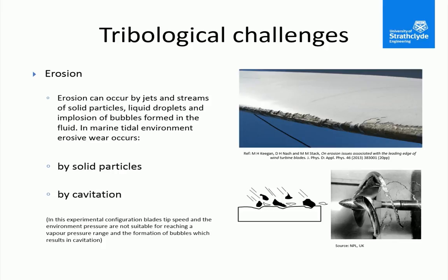We can also have cavitation erosion, where erosion results from the formation and collapse of bubbles under pressure. Erosion can enhance chemical degradation, and chemical degradation can also enhance or impede erosion. It's rather a complex situation.